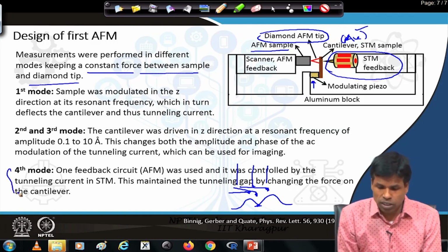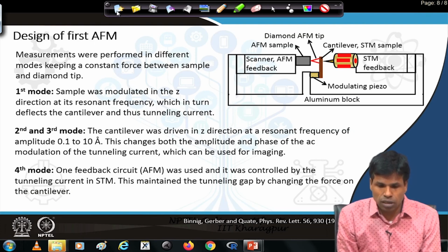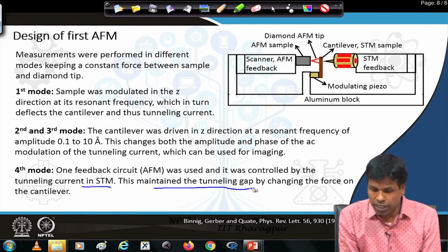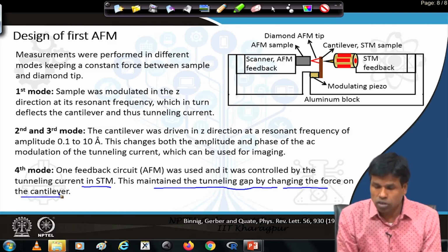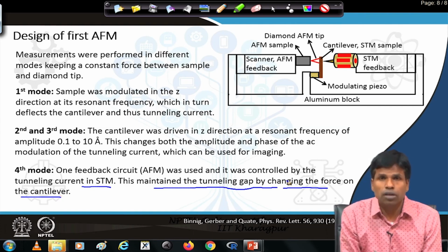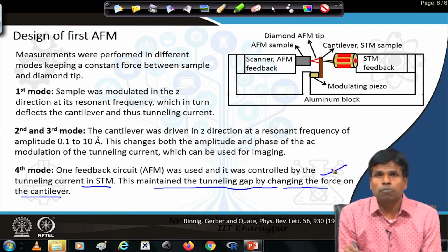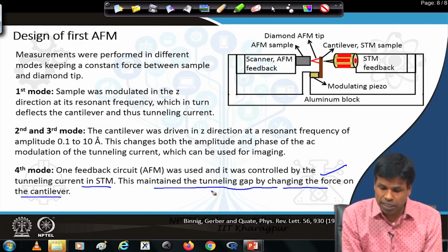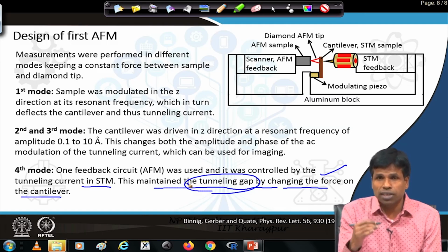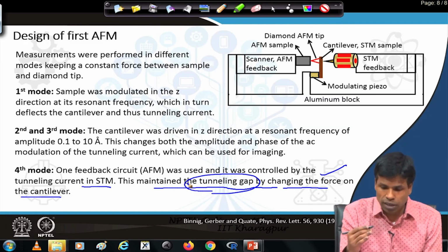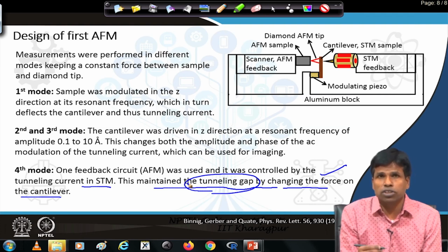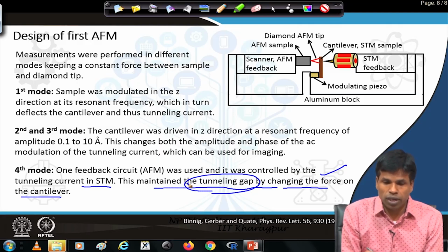In the fourth mode, it was not the constant force mode. Here one feedback circuit was used and it was controlled by the tunneling current, which was maintained by changing the force on the cantilever. So, in order to maintain the same tunneling gap, the same tunneling current, the force changes, and that force can be used to create a 3-dimensional image. In this way also one can create a 3D image of the sample.